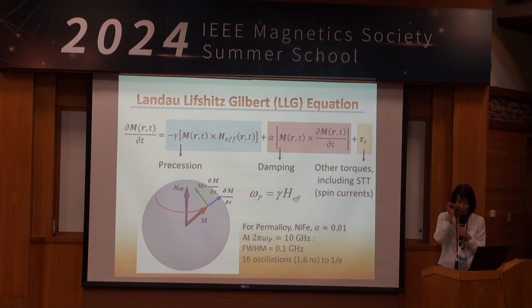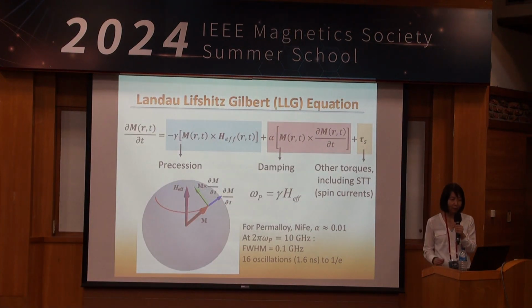Okay, I did say a magnon is an excited state, right? So for any excited state, you need to be concerned about its dynamics. And I'm sure you've seen this many times by now. The magnon dynamics are simulated by the LLG equation. In this formalism, a magnon refers to a small deviation from the static magnetization, and it's a rotation around an effective field. In this formalism, the precession frequency is the magnon frequency, and alpha is the damping.